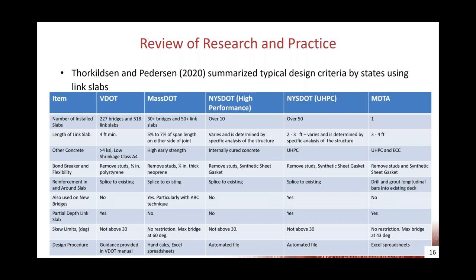But in general, we have a length of somewhere between 5 and 7% of the span, with some minimums depending on the state. The concrete that's used varies, from Virginia using a more conventional concrete, Massachusetts using a high early strength concrete, and New York using both high performance concrete and UHPC. But in all cases, they have a bond breaker over the pier and some connection to the slab reinforcement, whether that's a lap splice, a non-contact lap splice, or grouting bars into the existing deck. There's potential for these to be used on new or existing bridges, and we've seen that states have gone either direction with those.